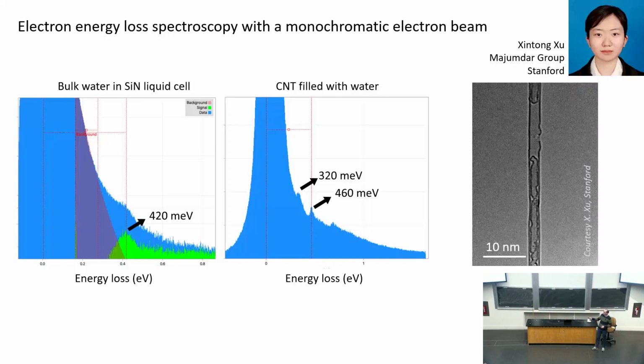And they allow you to do vibrational spectroscopy right in the TEM. These are very special electron microscopes with a very high energy resolution, and that allows you to see phonon modes. So one thing that they see or compare here is water in a silicon nitride liquid cell, and you have this sort of OH stretch mode, which is 420 meV. And when they look at a system like this, actually this mode shifts quite a bit to 460 meV. And we believe it's a signature of the interfacial water that is more free than the bulk water.